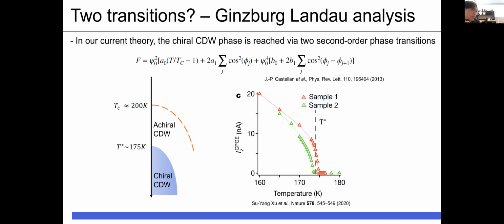If we suppose that M displacement is caused by a second order phase transition, then it's impossible according to Ginzburg-Landau theory. According to the Ginzburg-Landau analysis, generally a second order phase transition should involve order parameters of only one irreducible representation. In our case, because L phonon modes and M phonon modes have different irreducible representations, L and M phonons cannot condense simultaneously. So in our current theory, 2 second order phase transitions are needed to make chirality, which seems to be consistent with the observation from photocurrent measurement. However, in our research, we couldn't find any evidence of an additional second order phase transition below the known critical temperature.